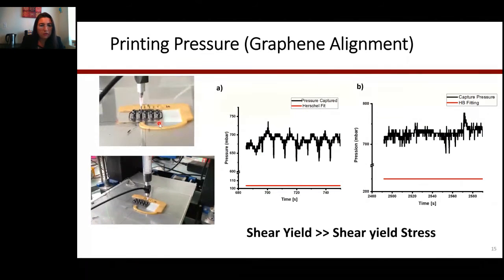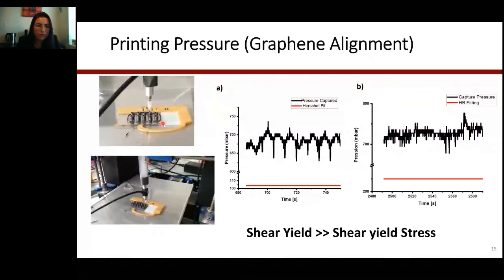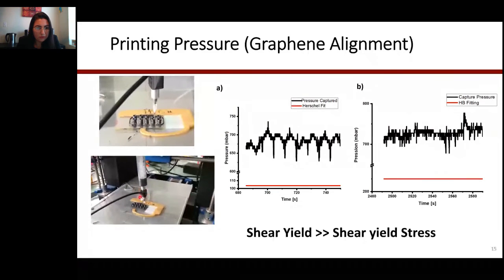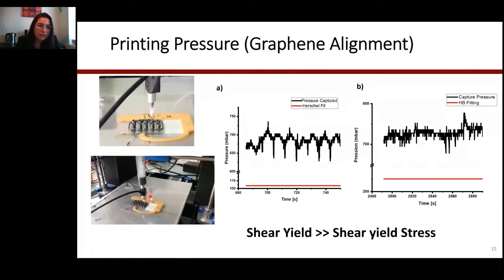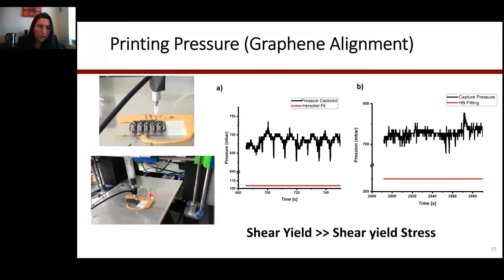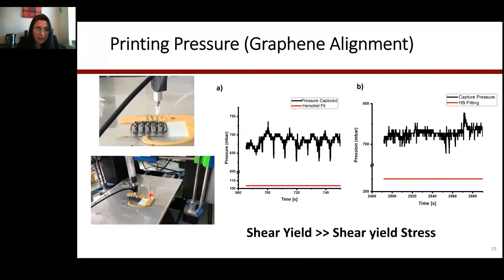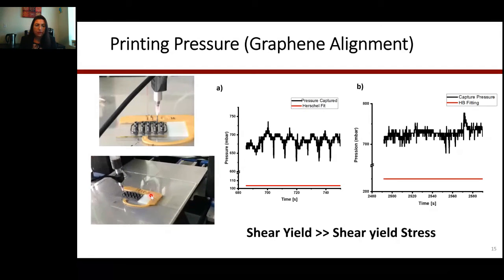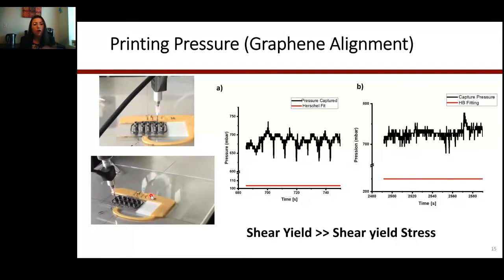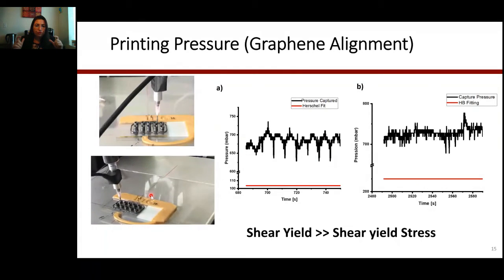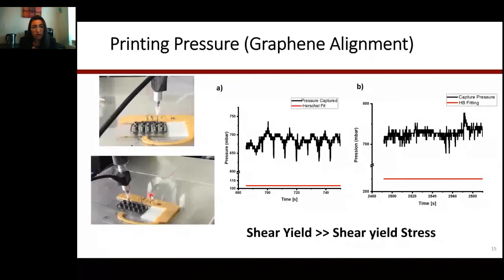On the video, as you can see, there is a black part on the 3D printer, and that black part is just a sensor that measures the pressure as you're printing. This pressure was really important to prove that we were actually having the alignment. In chemical engineering, when we learn about flow and plug flow, we ensure that the shear yield is exceeded. We did that for all our samples, and we were able to 3D print all the different samples.